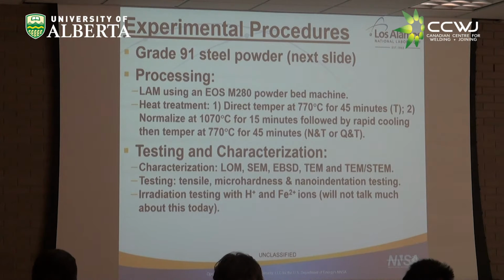Afterwards, we did a couple of different interesting heat treatments. Usually when you weld the T91 or P91 plate or piping, it's now connected to a big reactor. It's very difficult to go back and heat treat that. So it's given what's called a direct temper. You see the parameters there, 770 C for 45 minutes or less. Also, if you wish, you can take the part into a furnace and renormalize it, which is austenitizing and dissolving carbides, followed by the tempering procedure. Characterization involved light optical, SEM, electron backscatter, TEM, and STEM.